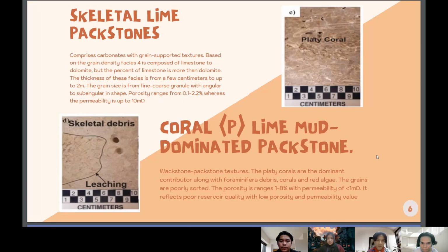So the fourth one is skeletal limestone. This facies 4 comprises carbonates with grain supported texture. Based on the grain density, facies 4 is composed of limestone to dolomite, but the presence of limestone is more than dolomite. The thickness of this facies is from a few centimeters to up to 2 meters. The grain size is from fine to coarse granule with angular to subangular shape. The porosity ranges from 0.1 to 2.2%, whereas the permeability is up to 10 md.